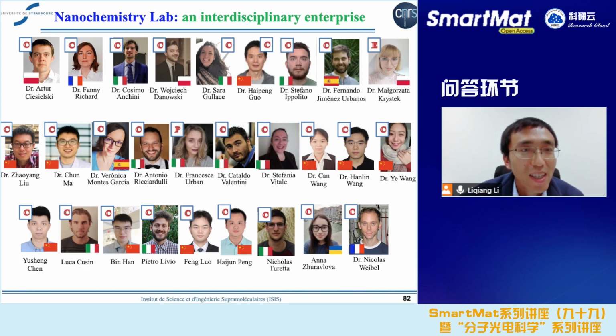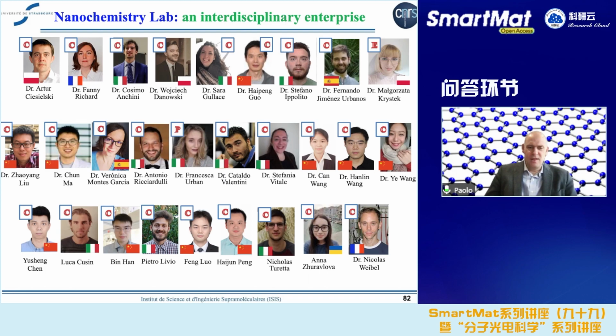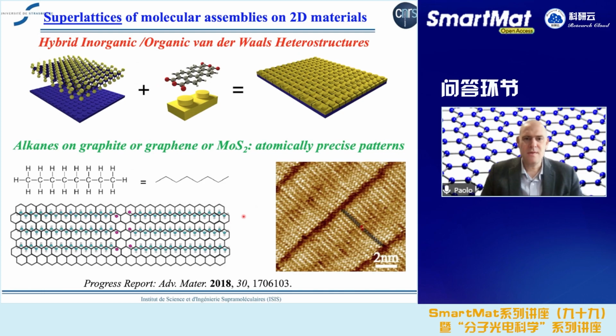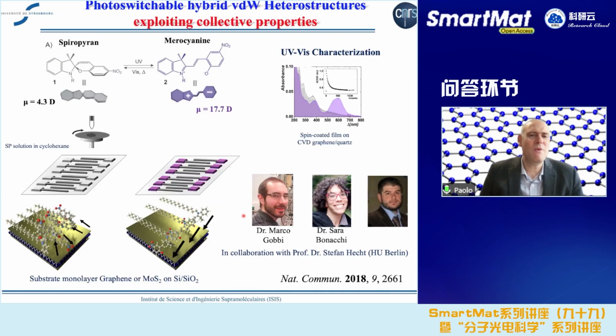Yeah, absolutely. That's a very good point. I showed two different approaches. Let me go to the slide so I can show you. The one with the spiropyran is the one where we play with the dipoles. Since here you want to control the orientation of the dipoles, the best is to have a continuous monolayer that covers the basal plane on the surface. Because if you have a thicker layer, I think it will be quite complicated to have full control over the orientation of the dipoles. And here, to maximize the effect, you really need to be able to control the alignment of dipoles. So monolayer-thick superlattices.